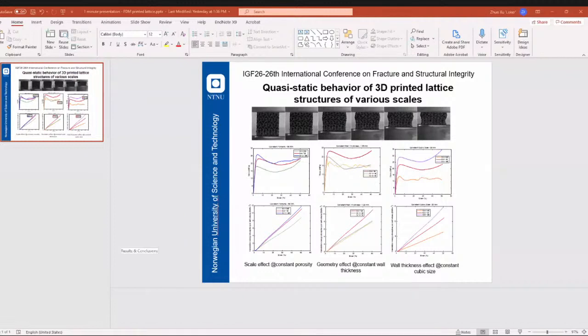So we found that all those lattices have a similar compressive behavior, except two of them. The curve shows some valleys and peaks, which indicates some possible buckling behavior. We need to do further analysis for that, so we're not that sure yet. And also for the cumulative energy, before the densification point of the lattice, all the curves showed an almost linear trend. So this is our main conclusion.